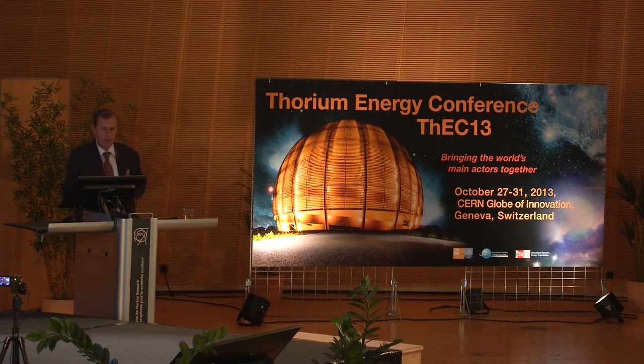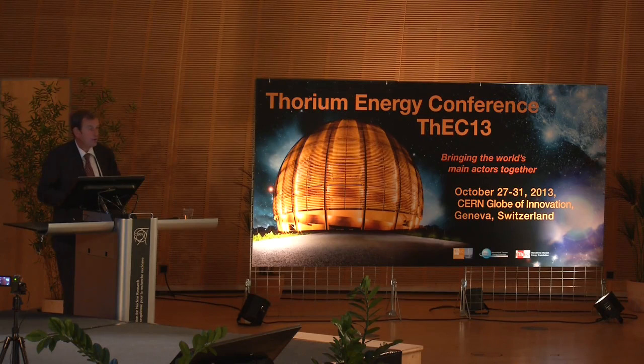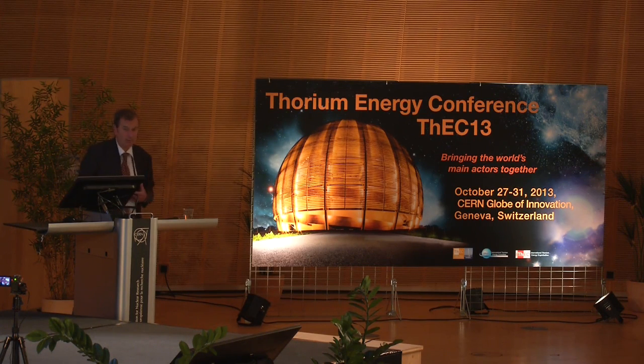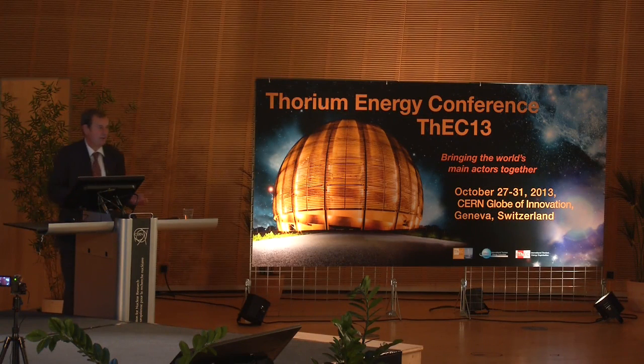So this was a selection in order to ease the process of the licensing of this material if it's used in the future, as compared to fully inert matrices, which are very different from UO2. Thorium oxide, moreover, is a very stable ceramic, which is important during reactor operation. It will not give different phases and complications in the use, but also in the disposal for the waste management. It's very important, and I will show you leaching test and corrosion test results on thorium. It's clear it's difficult to reprocess, but the advantage is it is also difficult to dissolve, and so it's very stable.